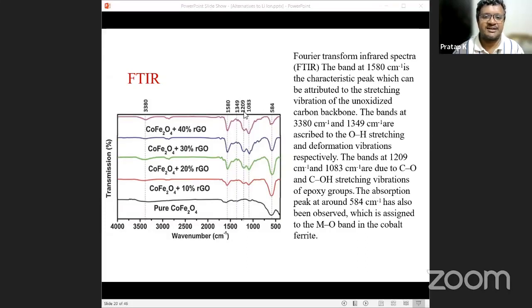And there is one more band at 1209 and 1083. So these are C-OH stretching vibrations. And you observe a peak here at 584. So this 584 is assigned to the M-O band in cobalt ferrite. So this is about the FTIR. This clearly confirms that we have prepared cobalt ferrite with different RGO compositions, and RGO compositions are increasing.